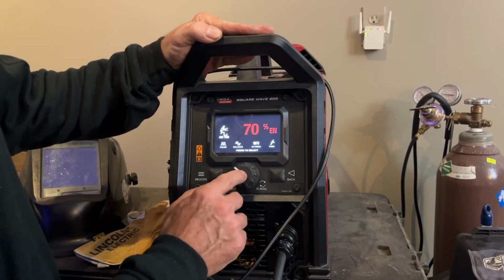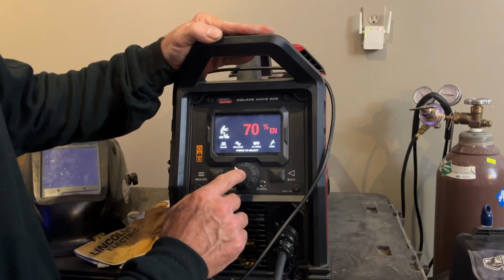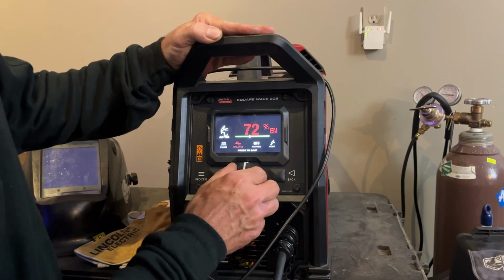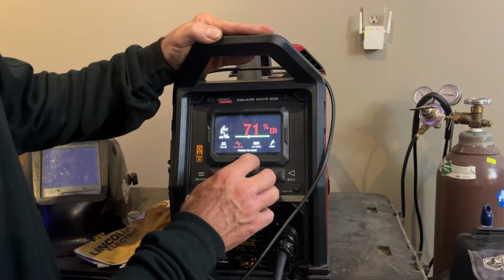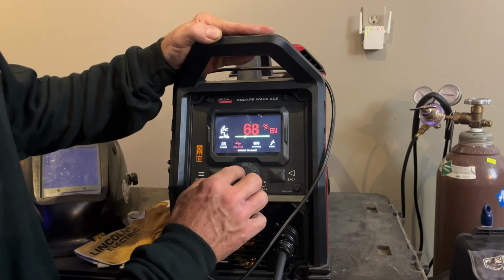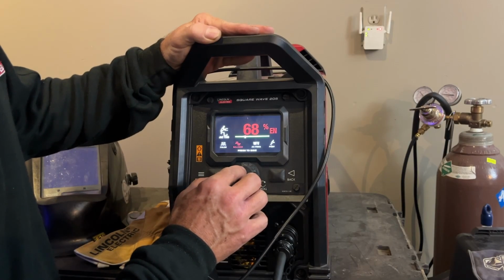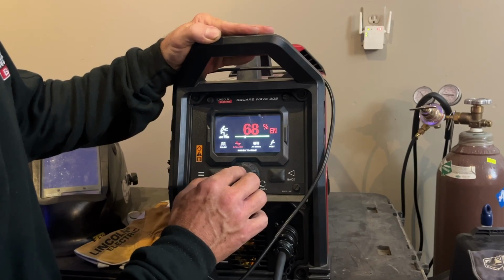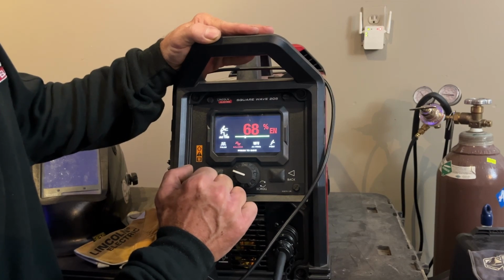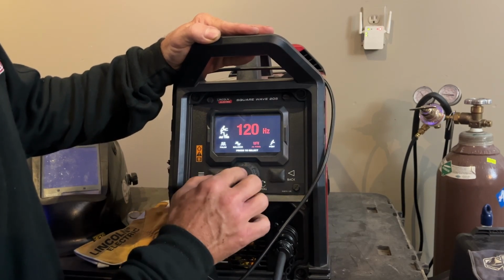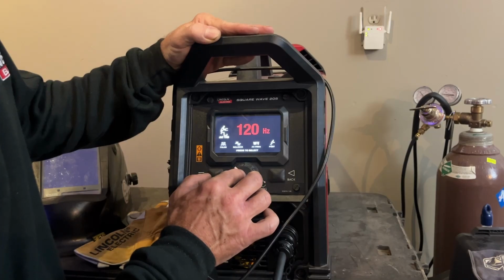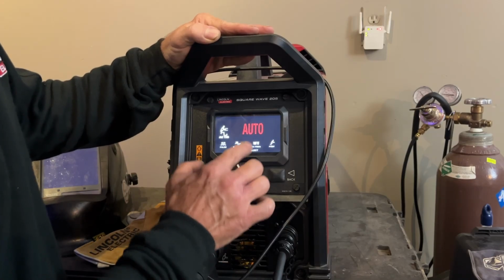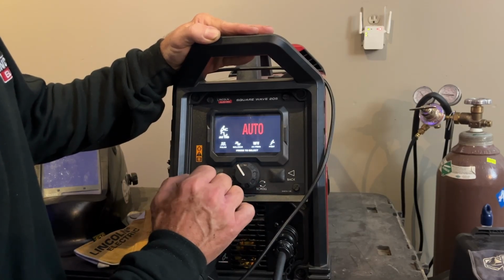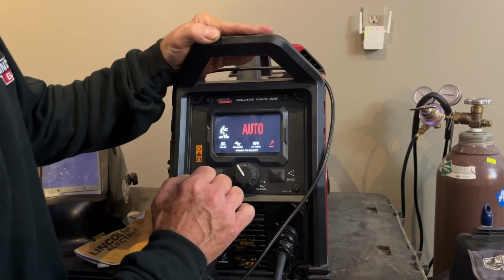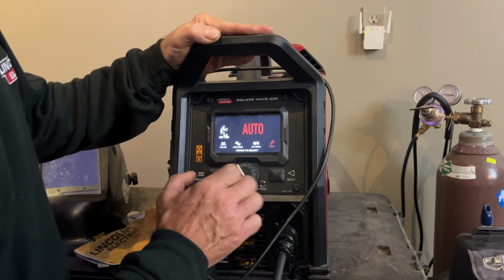Okay, let's take a look. My pulsar is off. My balance is around 70%, and a lot of times modern machines come out at about 75, so we're going to back that down. I'm actually going to go to 68% electrode negative, which is the maximum that older technology, like the older square wave transformers and the older Synchrowave machines, could get. All right, AC frequency, I like 120 hertz. Post flow, automatic. So it's going to give us 1 second for every 10 amps we're welding. That way we don't waste gas and we don't weld too hot and smoke our tungsten.